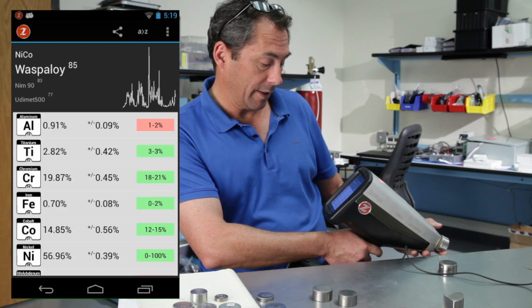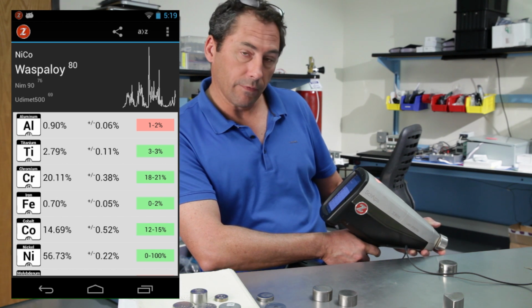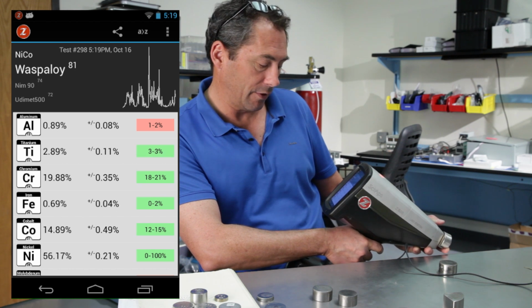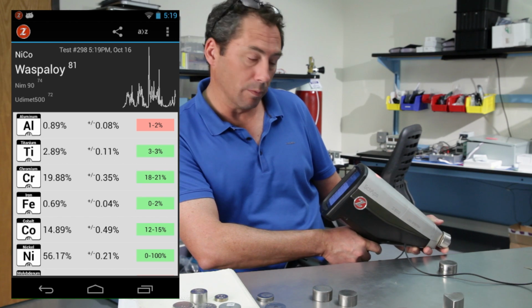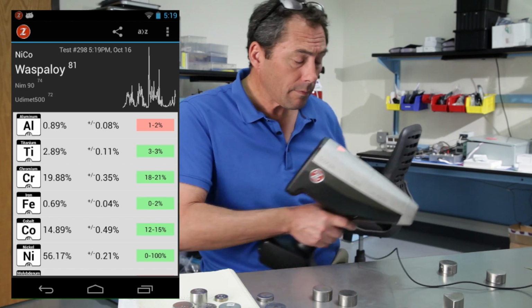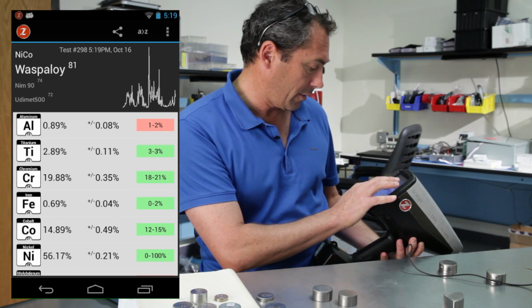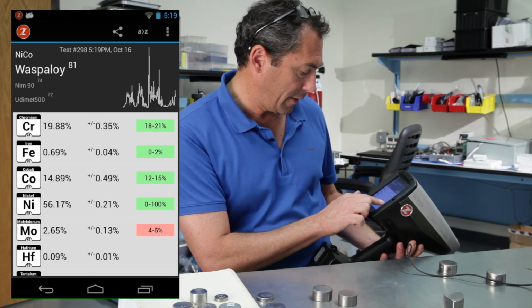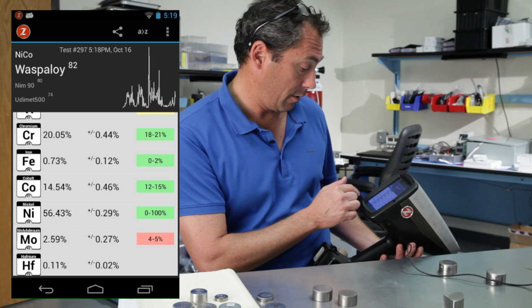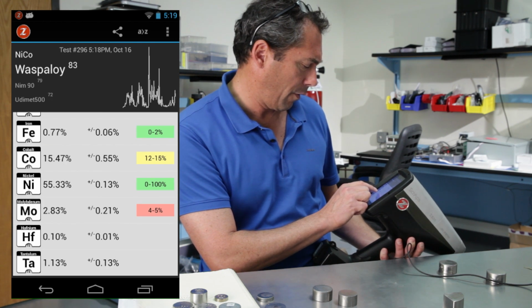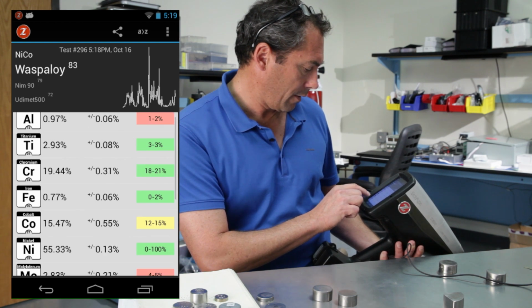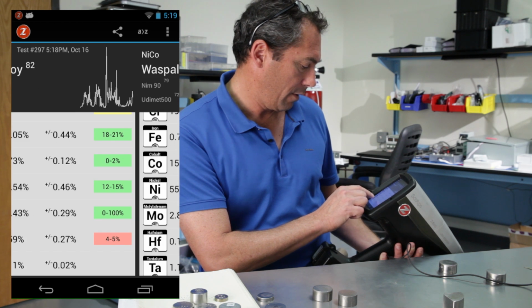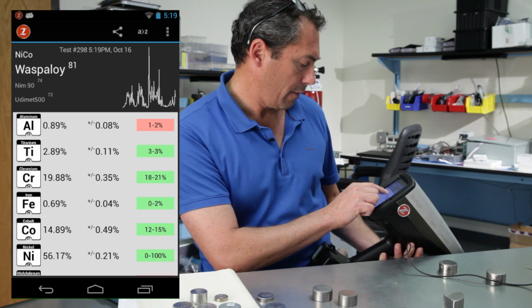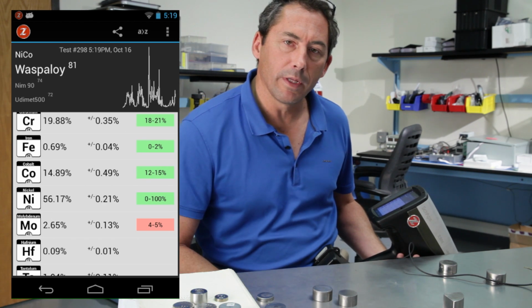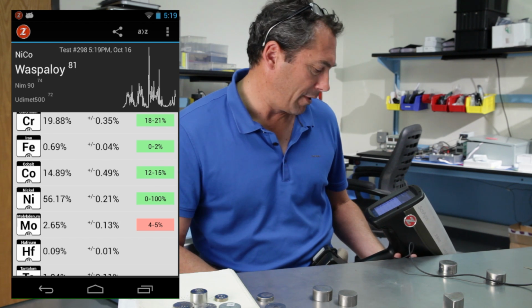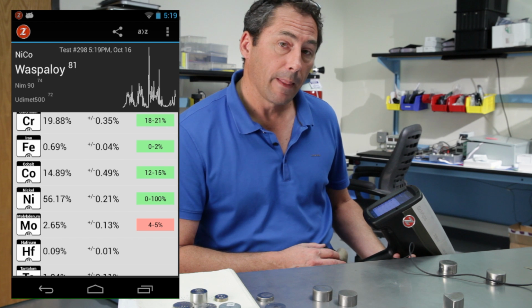One other thing I like to point out is that the aluminum measurement is very quick. There's several percent aluminum in a lot of these nickel alloys, and you see that right away with the LIBS, where you don't with the X-ray. You need the dual beam test. So that was the 3 Waspaloy readings. And if you look at the repeatability, let's just focus on nickel. Last 3 readings: 56.1%, 56.4%, 55.3%, and consider the cobalt: 15.4, 14.5, 14.9. So the nickel is like plus or minus about 0.3, 0.4% maybe. Cobalt a little bit higher than that, but that's all right. So that's pretty good for a 4 or 5 second test on a laser-based unit.